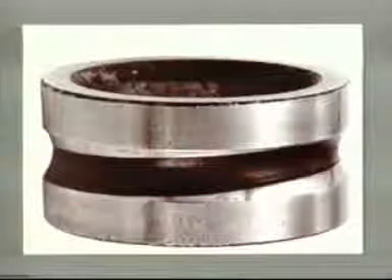When the seats of non-aligning bearings reveal large misalignments, then a so-called detrimental misalignment preload takes place. The inner and outer rings are tilted against each other. The rolling elements then run under inner restriction in the apex zone. One characteristic of this phenomenon is a diagonal groove on this stationary ring.